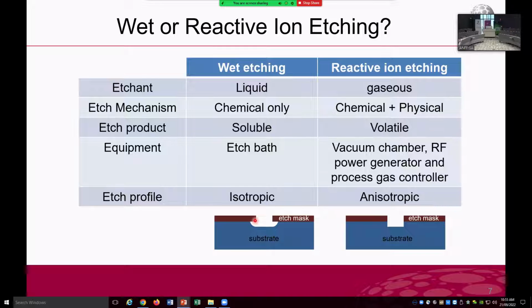So there is always a shift between your etch mask and the etch structures you finally get at the end of the process. But in reactive ion etching, the aim is to control the etch rate, increasing the etch rate in the vertical direction and suppressing the etch rate in the horizontal direction. By doing this, you can achieve these vertical etch profiles. We call that anisotropic etch profiles. Etch rates are different, and this is the biggest difference between wet etching and reactive ion etching.